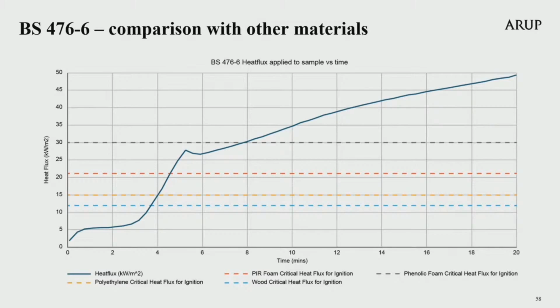I have used dashed lines to overmark the graph with values of typical critical heat fluxes needed for the piloted ignition of the materials. This is the ignition that occurs when a flame is impinged on the specimen. I have provided those classic and typical values for PIR foam and phenolic foam, polyethylene and wood. Therefore, with the heating dose from the Part 6 test, the applied heat flux to the sample made of wood, the wood would be expected to ignite between 3 and 4 minutes. For polyethylene, this would be after 4 minutes. PIR would ignite between 4 and 5 minutes, and phenolic foam after 8 minutes. The Part 6 test is a total duration of 20 minutes.